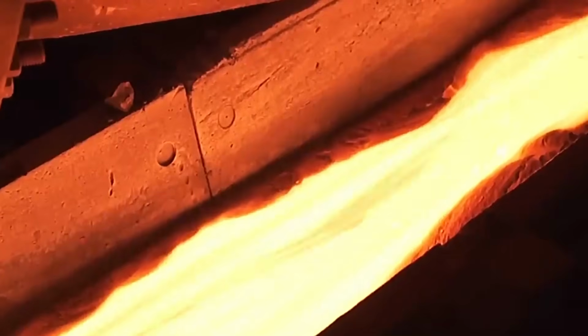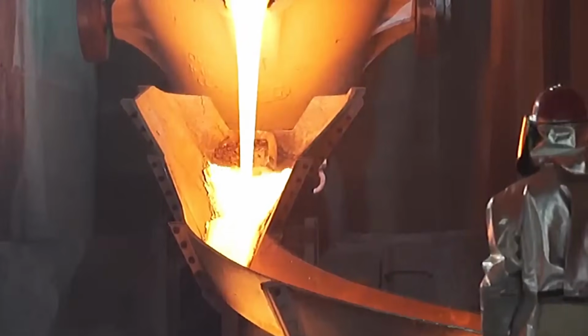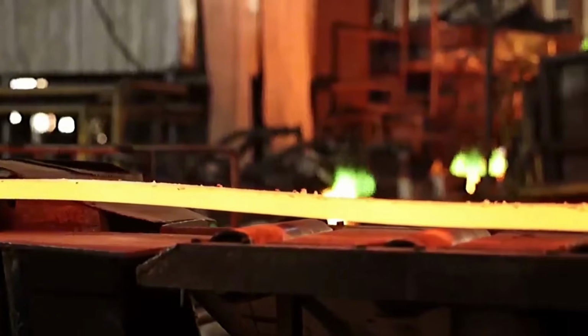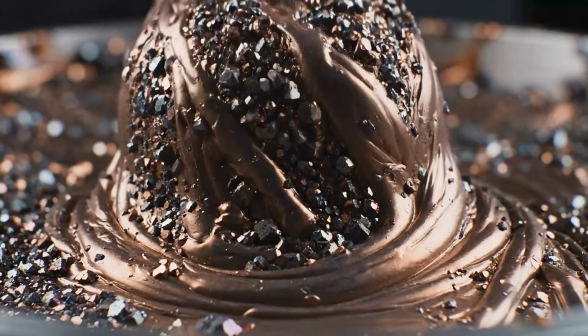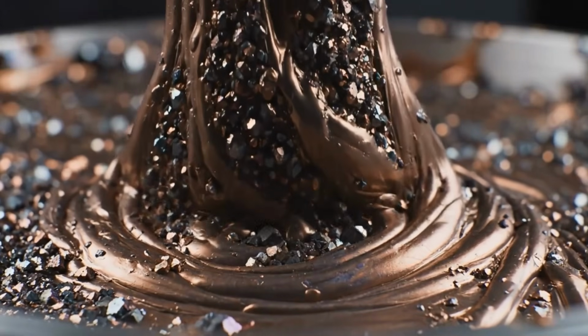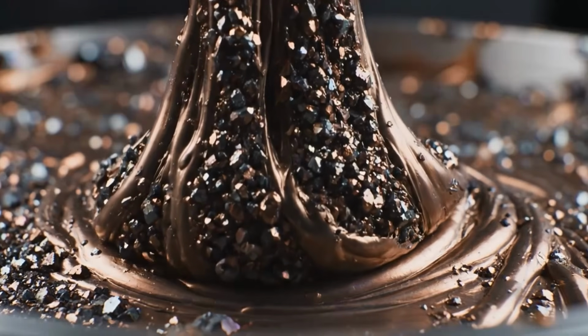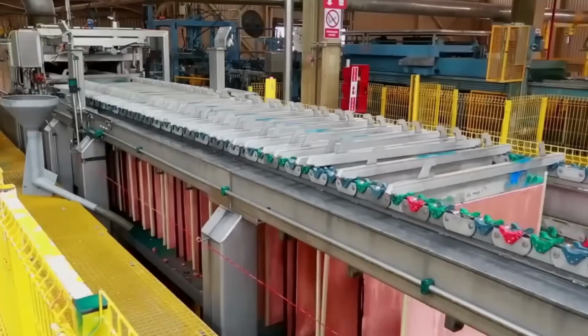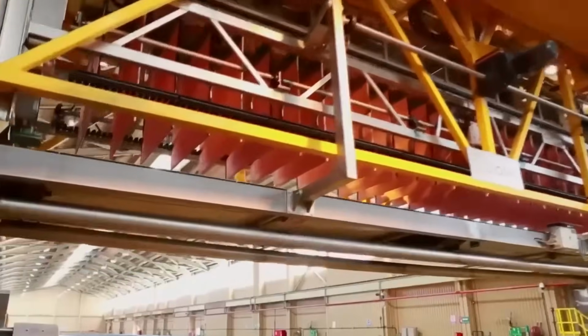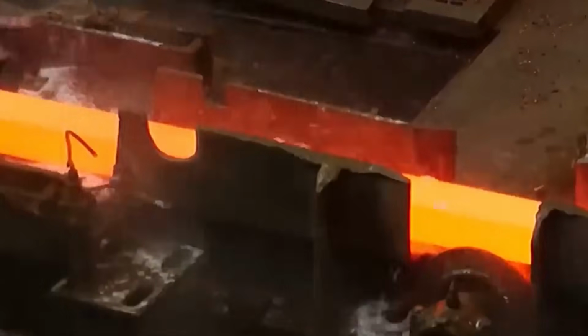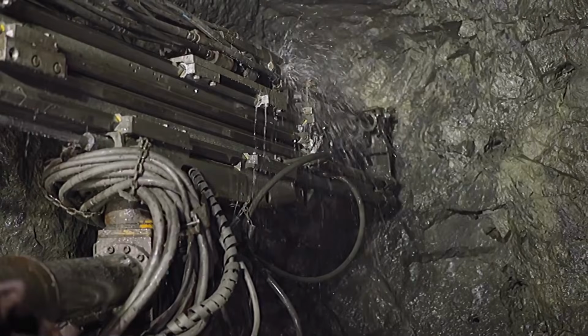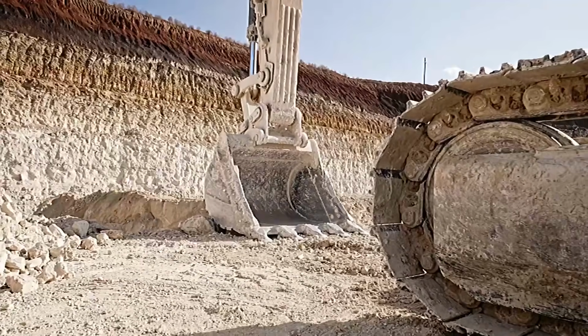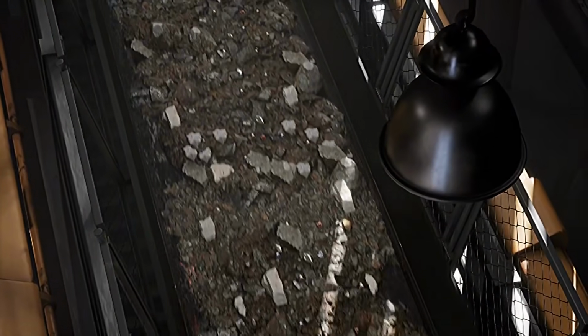Quality control teams use electron microscopes to examine copper cathodes for microscopic impurities that could cause electrical failures months or years after installation. A single grain of unwanted metal measuring just a few micrometers can create a weak point that leads to power outages or equipment failures in critical applications. The testing process involves dissolving sample pieces in acid and analyzing the resulting solution with spectrometers sensitive enough to detect impurities at the parts per million level.